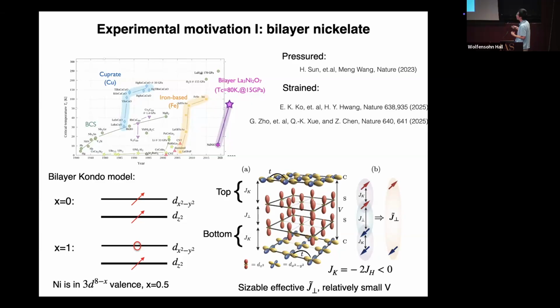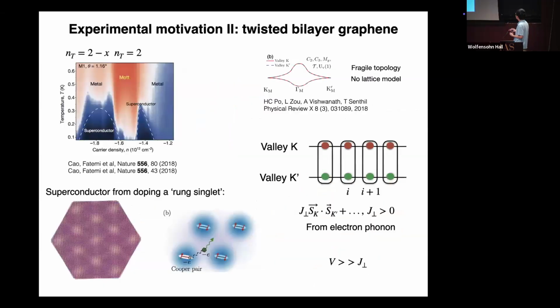So this is one experimental motivation. There's another experimental motivation, twisted bilayer graphene. This was found 7 years ago. This is from the experimental paper. You can see, when you twist the 2 graphene layers by a specific angle called the magic angle, 1.08 degrees, you generate a larger superlattice. This lattice constant is on the scale of 10 nanometers.